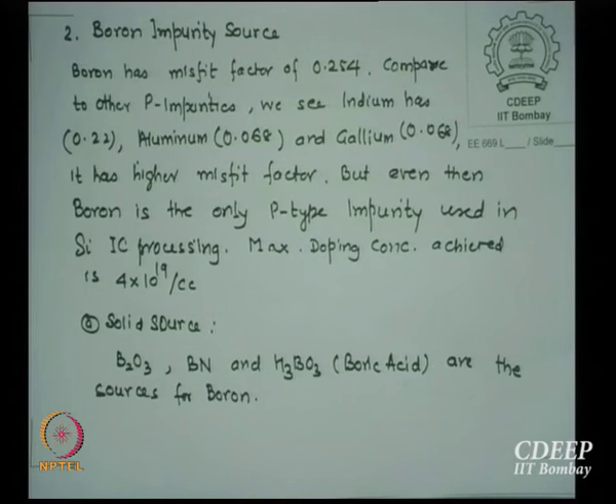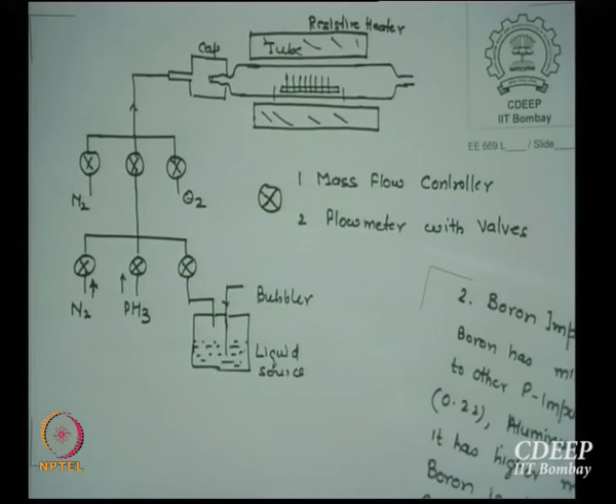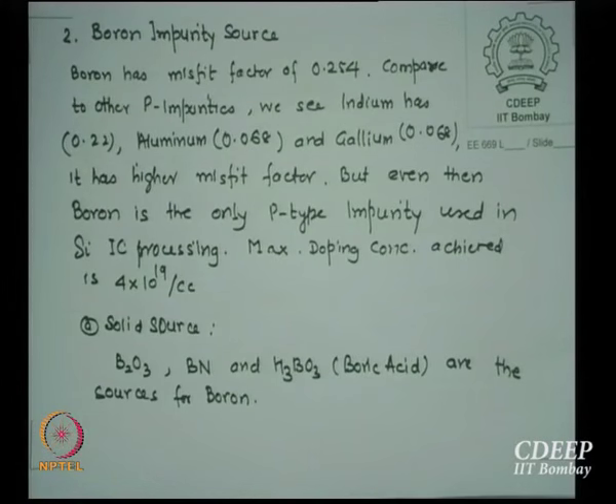Then, we have seen phosphorus, let us look at boron. This figure has nothing to do with phosphorus, this is for all kinds of diffusing systems. As I say, aluminium and gallium have a better misfit factor than boron. Indium has 0.22, boron has 0.254. Even then, we only use boron. As I already said, aluminium is bad, it forms an alloy, so we don't want to use it. Gallium has a very large activation energy, so we don't want to create very few holes. Indium is also 0.16 electron volt, so we don't want to use it. Boron has 0.086 as the activation energy, so it's used very extensively.